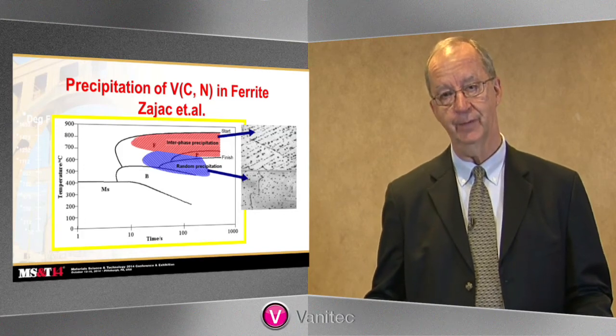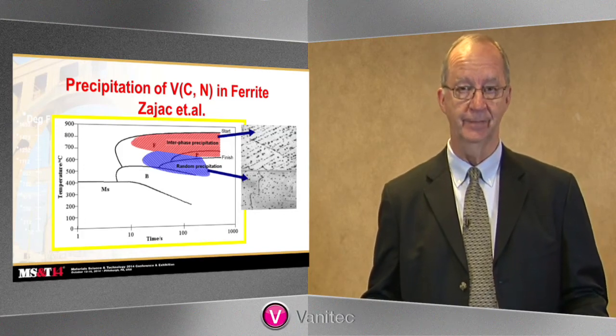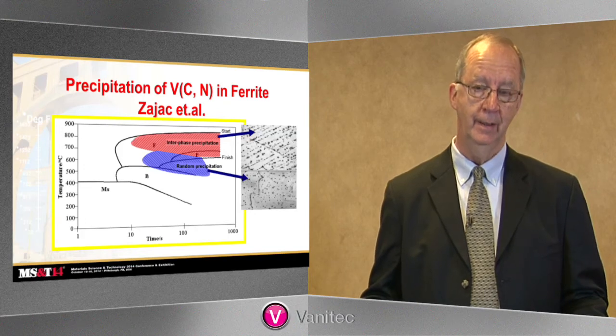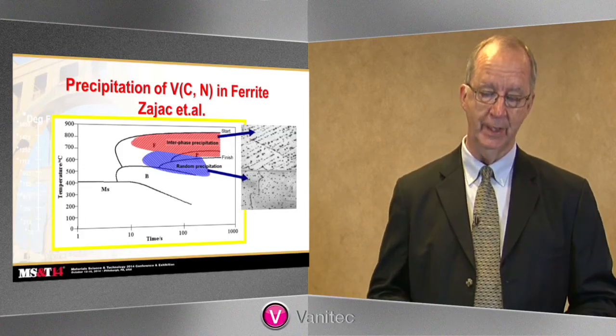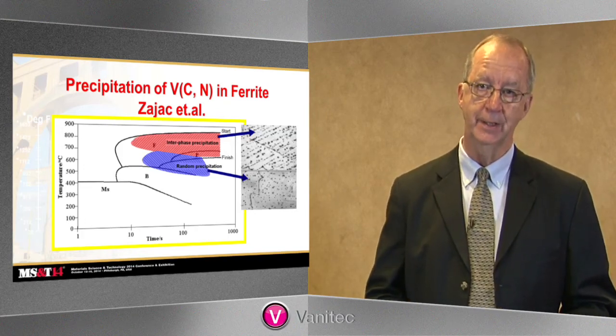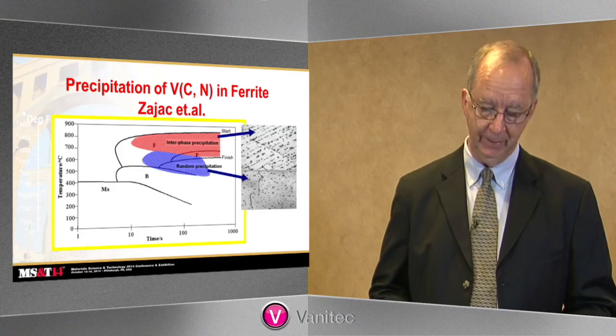If it's only carbon available, typically that number is less than 50%, maybe 20 to 40. That is the primary reason why you see the differential strengthening rates between the vanadium nitride and the vanadium carbide.